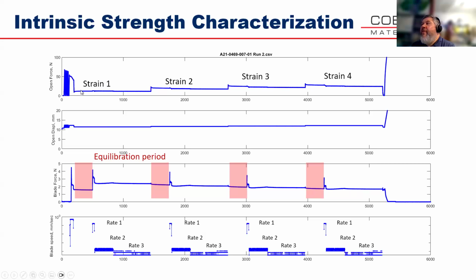After the precondition, then we go to the first strain and hold. And then the second strain and hold, and then the third strain and hold, and then the fourth strain and hold. The hold period, if you look at this, is about 10 minutes per step. Now, once we are holding at fixed strain, this third chart here is showing you the cutting force on the blade that's cutting the strip of rubber.